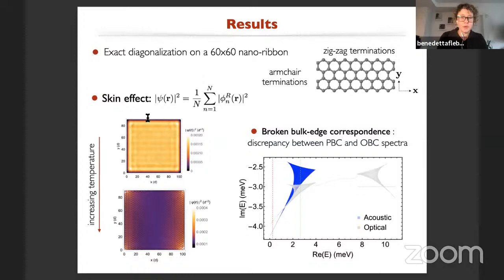So when we are at low temperature, here I think it's around 2 Kelvin, what we see is that all the bulk bands are delocalized throughout the sample. This is what we would expect from a Bloch band type of description. So there is no skin effect, and this also confirms our usual assumption that in the long wavelength limit, things are quite well described by non-exotic effects. But if we start increasing the temperature, so here we are reaching this point, we observe the emergence of the skin effect. So the wave functions start localizing macroscopically at some edges of the sample. They are not distributed anymore inside the system.